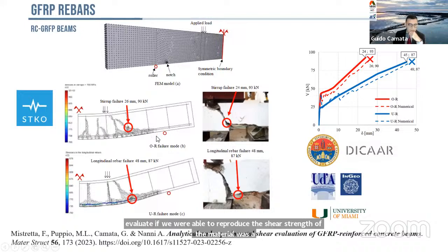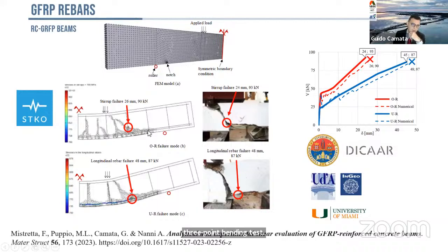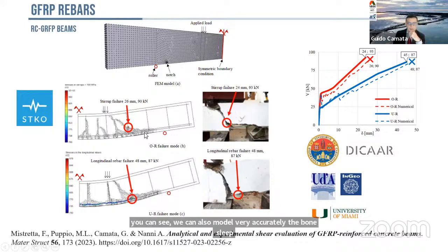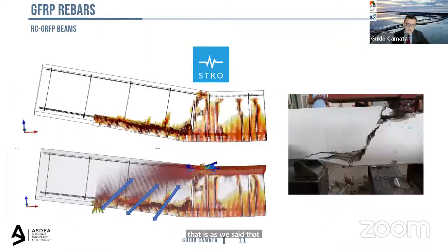As I said, we performed several. As you can see, we can also model very accurately the bond slip and the loss of anchorage of the GFRP rebars and the shear failure. And as you can see, these models are able to reproduce the experimental results quite well, because if you see, the numerical is 90 and the experimental is 93. This gave us a lot of insights regarding the stresses on the rebars, and especially the stresses on the bend. It is, as we said, the most important thing to evaluate.